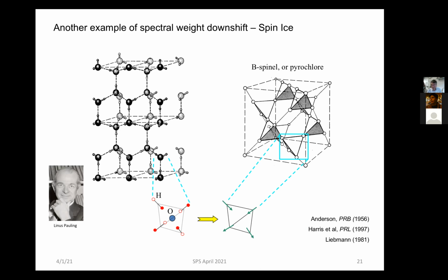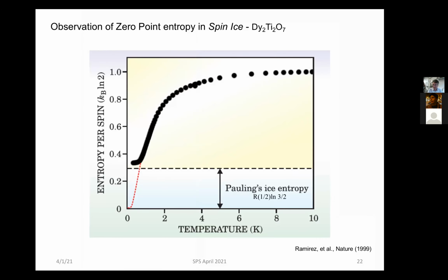Well, we found a magnetic system that behaved like that. It's called the spin ice pyrochlore, where you can map the hydrogen degrees of freedom onto spin degrees of freedom. And I did this measurement in 1999, where I showed that you don't get all the entropy out of the system. Spins are great because they can have low energies where all the other excitations are frozen out, and they have a fixed amount of entropy. A spin one-half can be up and down, so all the entropy you get out is R log 2, where R is the gas constant. And I measured the shortfall, and that shortfall was extremely close to what Pauling predicted for ice.